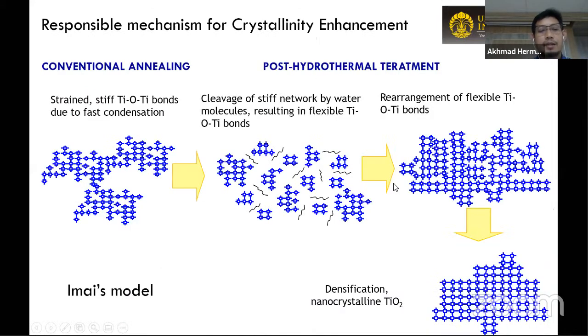Next slide, please. This is the mechanism of why the crystallinity is enhanced by post-hydrothermal treatment. Previously, with the sol-gel method, we always have amorphous material, but with post-hydrothermal treatment we can rearrange the flexible TiO2 bonds to get more densified nanocrystalline TiO2. This is the secret behind the crystallinity enhancement by post-hydrothermal treatment. Next slide, please.